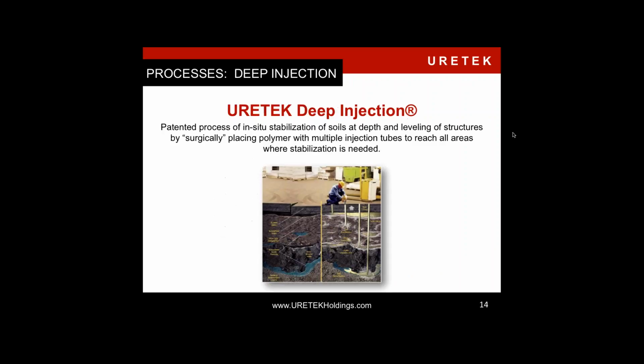The second process would be the deep injection. That is injecting high-density polyurethane in situ, meaning in place, directly into the weak soils, and that is determined by pre-testing, soil testing, to determine where the soils are weak and increase the load-bearing capacity of those soils by deep injecting high-density polyurethane.